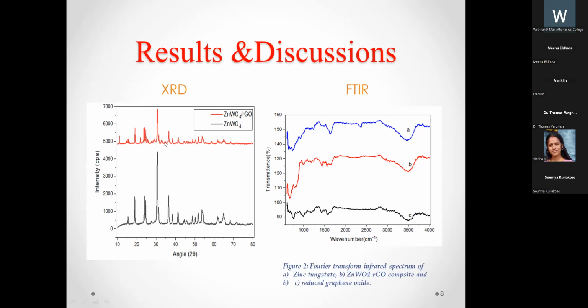Moving on to FTIR, A, B, and C represent the Fourier transform infrared spectra for zinc tungstate, the RGO composite, and reduced graphene oxide respectively. Here the peaks are almost the same for all. RGO shows a band at 3500 because of hydrogen bonding, and similar is the case with zinc tungstate, because we are synthesizing this material in aqueous solution, so it also shows an FTIR peak in the 3500 range.